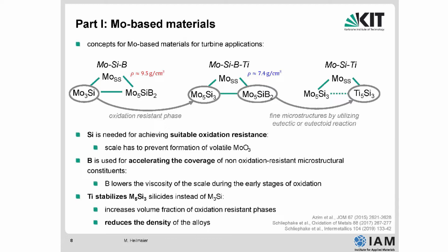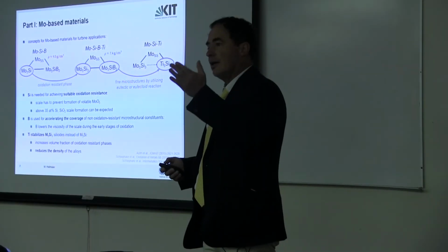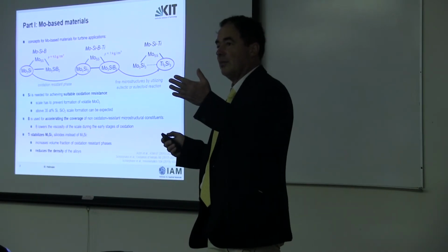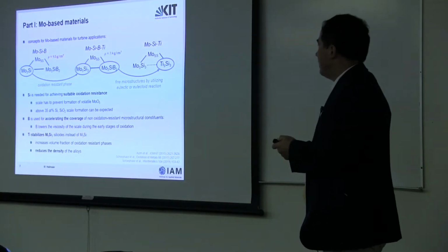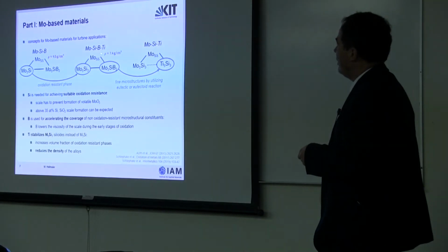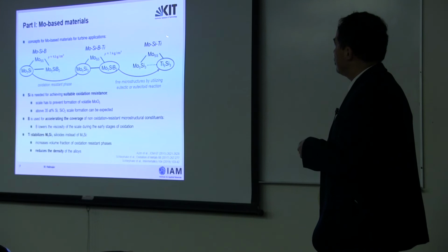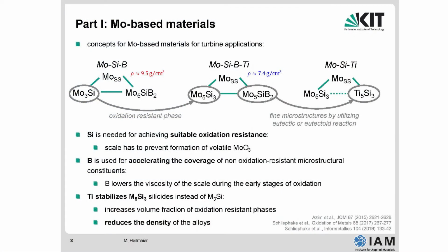And this can be done by titanium, for example. Titanium addition changes also the phase formation somehow, but you can avoid this by playing around with the phase diagram. I don't show this slide here. But then at the end, the density is down to 7.4, which is lower than nickel-based superalloys. So we have an alloy which has a potentially higher oxidation, higher creep resistance, mechanical strength at high temperature, but has a lower density already. Now you could ask yourself, why at all do you need the boron? And this is what I will show you in the next few slides on this first part.